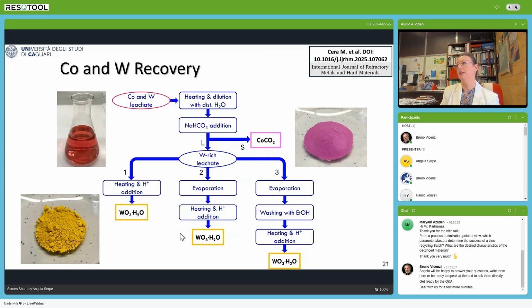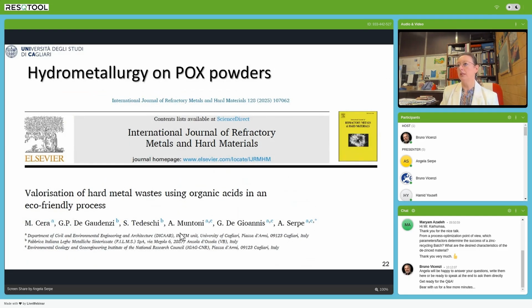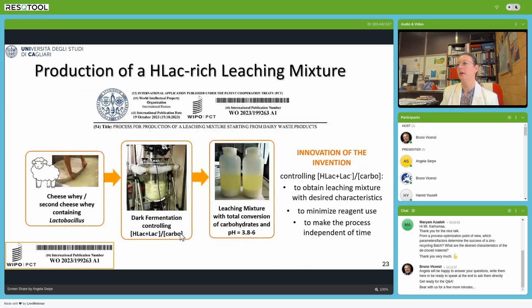So typically cobalt is recovered from the leaching solution as a carbonate precipitate, adding bicarbonate salts, and instead tungsten oxide can be precipitated in acid environment. So also this part has been published, and you can find more details in this paper.